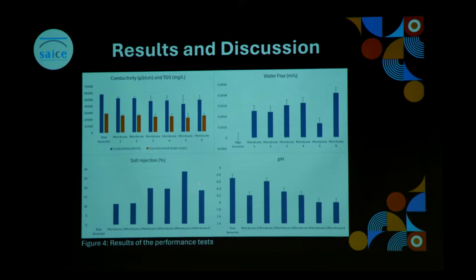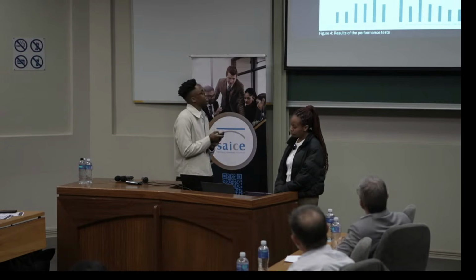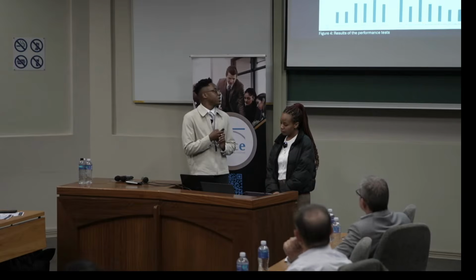When we turn our attention to membrane 6, we can clearly see that performance drops off, with salt rejection falling back to around 18% and the conductivity rising in comparison to membrane 5. This shows us that previous findings showing that excessive PIL can disrupt membrane performance are true. The reason for this is that the excessive PIL disrupts the membrane's pore structure, making it less selective. So in other words, instead of enhancing rejection, the amount of PIL added, starting at a certain point, will start to compromise the balance between permeability and selectivity.